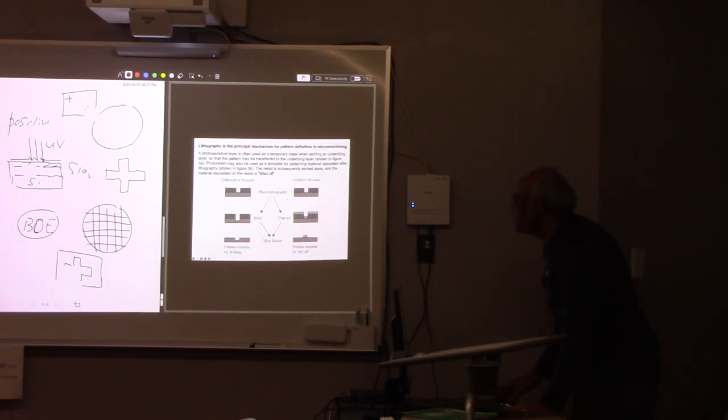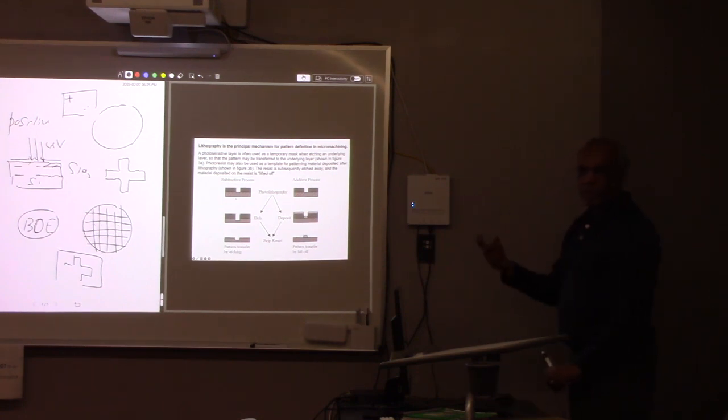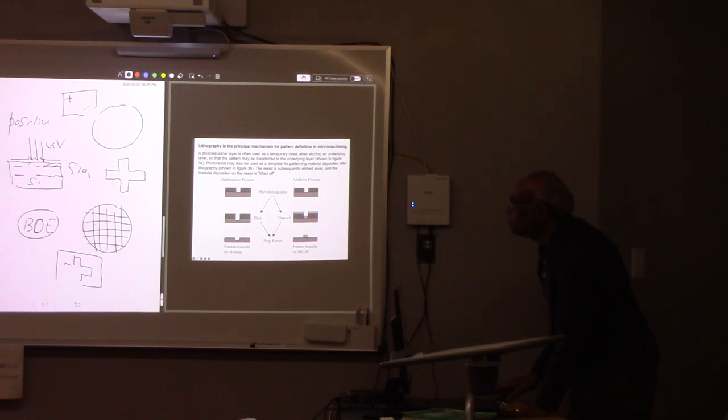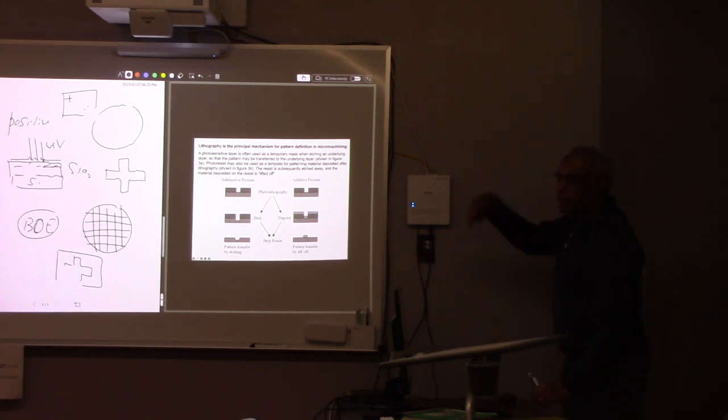This is what I explained to you, right? This is the silicon dioxide part, and this is the photoresist. This is basically a positive photoresist after exposure. Now if I put this in the BOE solution, a buffer oxide etchant, what will happen? This part is protected, so only this part will be etched like this. Now if you do the removal of the photoresist by putting it in acetone, you remove this one, and now you have this pattern carved in, right?